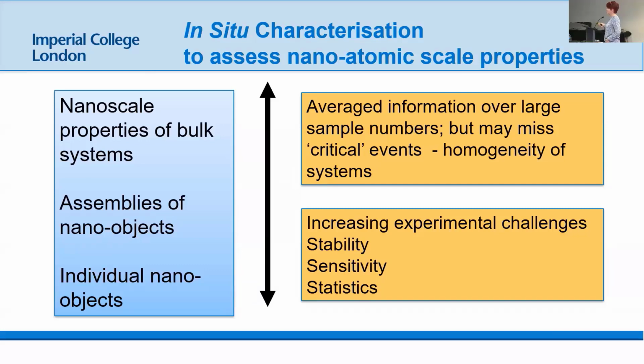You can get averaged information over a large scale and assume that you can deconvolute that out, and that is really good for statistics and signal to noise, but you might miss some of these critical events that only happen one in a million times, and you don't ever see that when it's averaged out. But as you go down to try and look at some of these really small objects at the right length scale, especially in situ, the experimental challenges become much harder. So you have to really think about the stability and the sensitivity and again, statistics. You look at one nanoparticle, how representative is that of the whole system? This idea flows through all the work that we do, that we have to really be critical about how you are measuring your system.